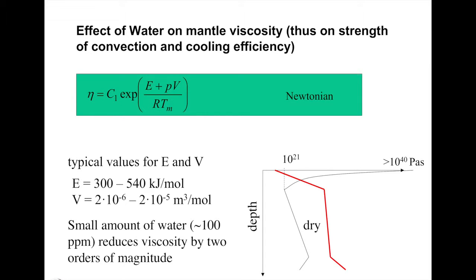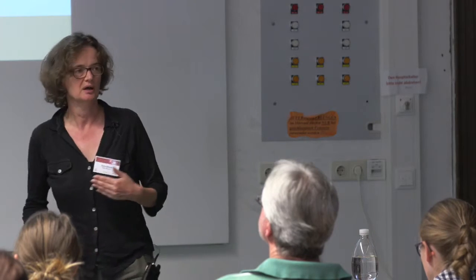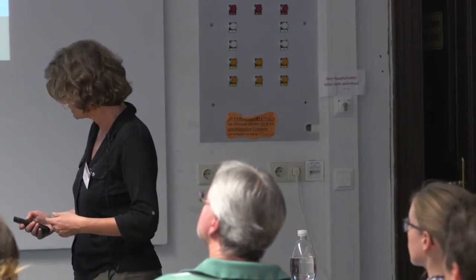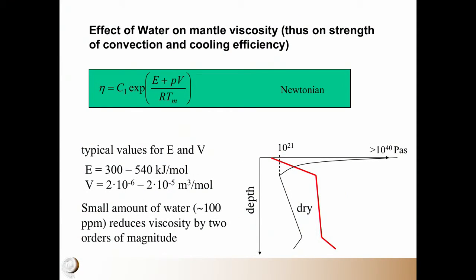The next point, which is also very important, is the effect on the mantle viscosity. The mantle viscosity more or less determines the strength of convection. If you have a low viscosity, convection can be very efficient. If you have a high viscosity, the convection is more sluggish, and also the cooling is less efficient. The stronger the convection, the stronger you can cool the planet. What you see here is the Newtonian relation of the viscosity with the activation energy, pressure, and activation volume. But the most important point is that it is inversely proportional to the temperature. That basically means for low temperature you have a high viscosity.